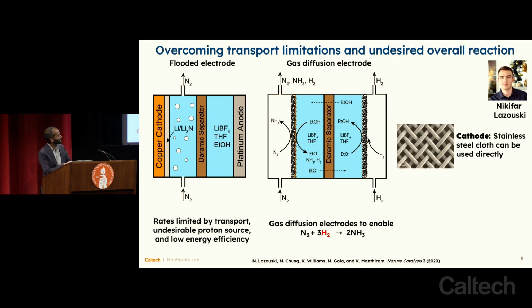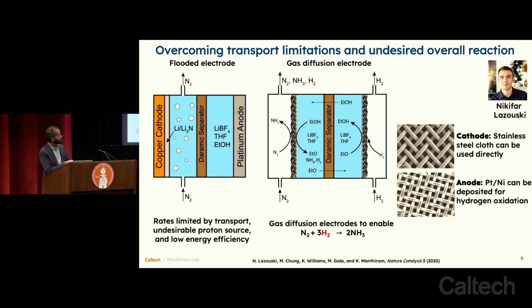And so we implemented the stainless steel cloth as a means of driving this reaction, so that's what we're using as a gas diffusion electrode. And at the anode, we did the exact same thing. Here we're oxidizing hydrogen, and we're using a platinum catalyst that's deposited on the surface. So this was our first step towards trying to solve this transport limitation within this reactor.